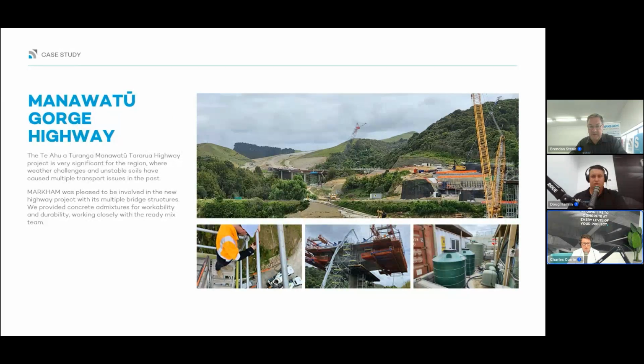Moving on to the Manawatu Gorge Highway, really known as Te Ahu a Turanga. This is a recent project we're involved in, the bridge superstructure. There's quite a bit going on there, but one of the main reasons we got involved with a durability admix was for workability. There was a microsilica content, I think about 8% off the top of my head, and a number of challenges with this, namely the stickiness of the mix. They did a large pre-trial on site, pouring hollow core beams, and that went really well on the side of workability. The advantage for the long term is that this is a real significant asset as part of the new highway, and by making that concrete impermeable, they get the advantages of long term durability.